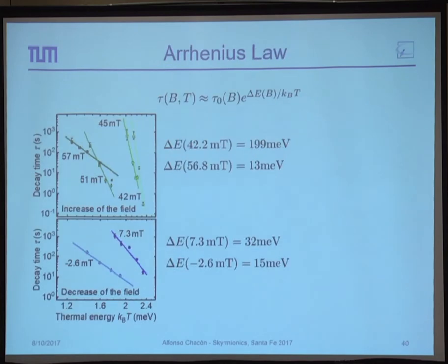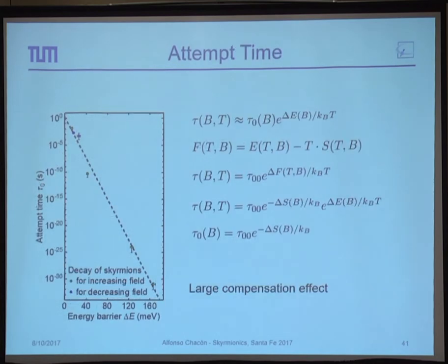What is important is this tau naught, and normally you would expect this tau naught to be in the range of about 10 to the power minus 9 or 8, something like that. And what we see is this strong dependence of the energy barrier over several orders of magnitude. And that's very uncommon, and we're not certain where it's coming from in the case of these structures.